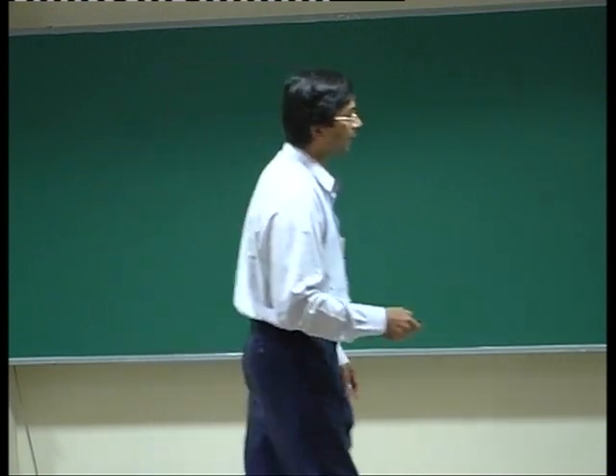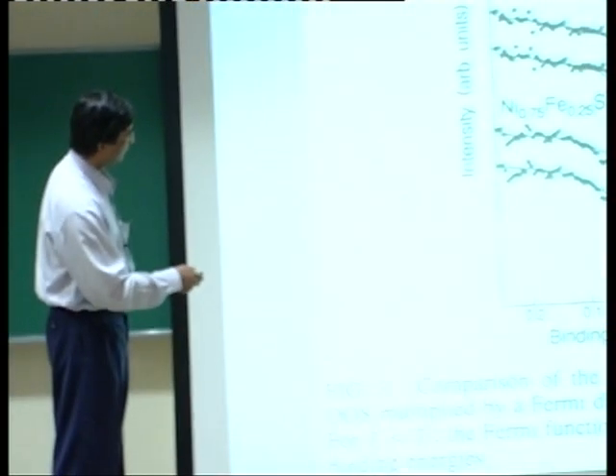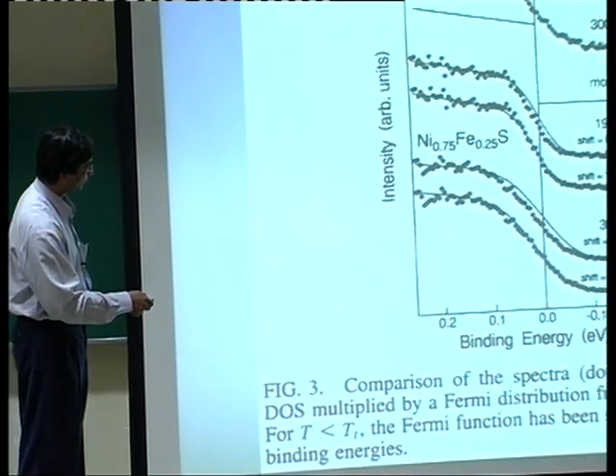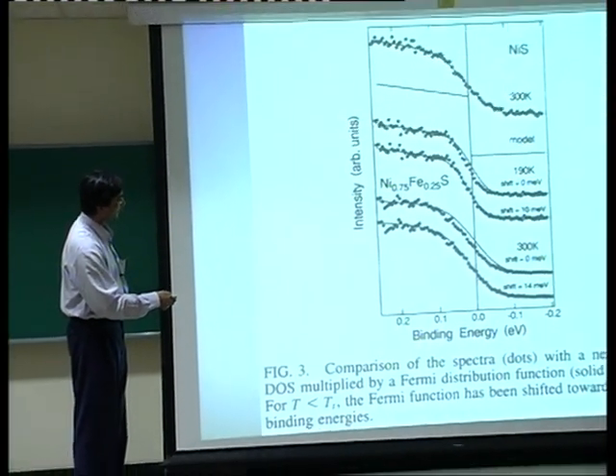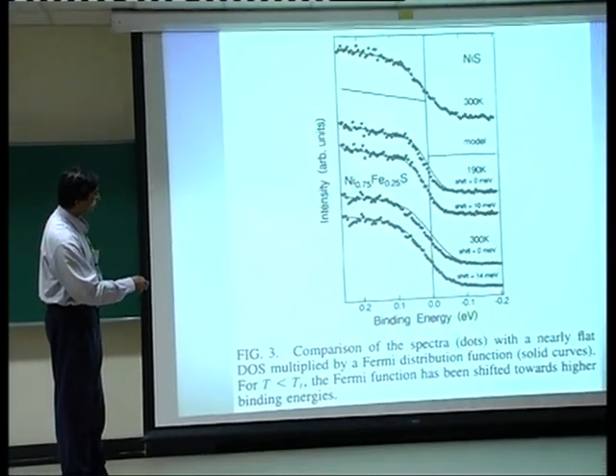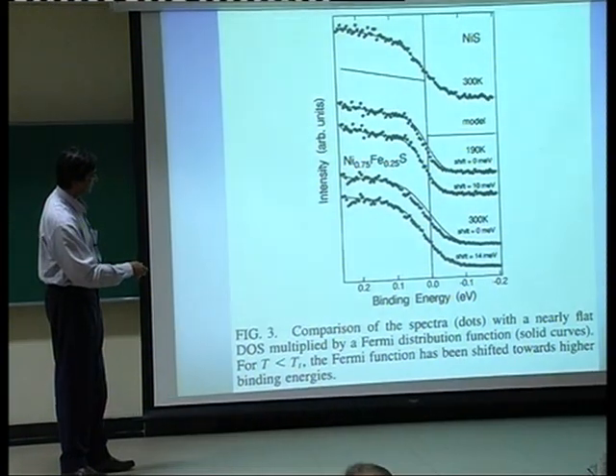Wonderful. Now then they went to the 190 Kelvin, and this is the experimental data. The solid line is still the solid line that you had here. And you can see that there is a slight shift. The actual experimental data at low temperature is shifted to the left with respect to the room temperature density of states.